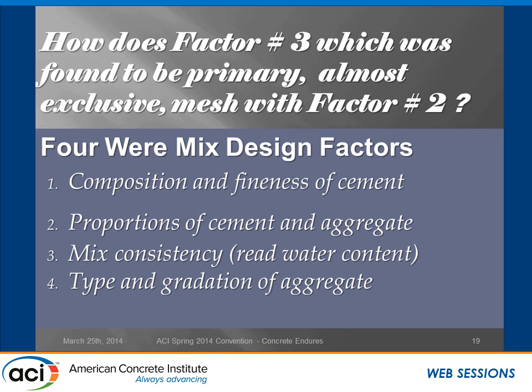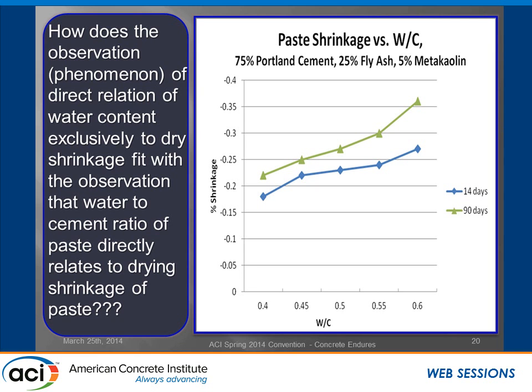So it's still an embryo, because we also noticed, in that earlier 1938 report, the composition and fineness of the cement, proportions of cement and aggregate, mixed consistency, water content, and type and gradation of aggregate, well, those were four things too. Some of those don't correlate with the water. How does the observation of a direct relationship between a water cement ratio and shrinkage correlate with what was going on there with the water content?